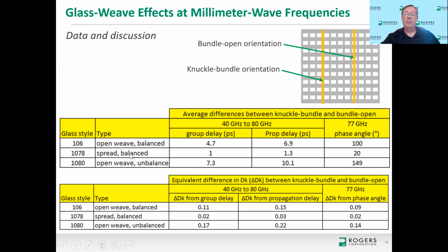Now, the next row down is the 1078 glass. So it's the exact same laminate, except a different glass. And this is 1078 or spread glass. And now you can see the difference for phase angle is significantly improved. So there's very little difference actually for phase angle at 77 gigahertz between the circuits of the different circuit glass orientation. And then finally, the worst case scenario was the 1080 glass last row.